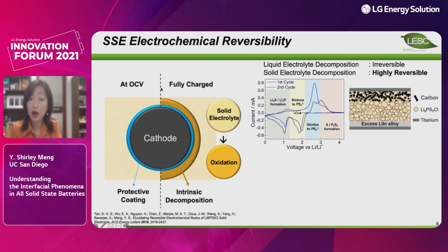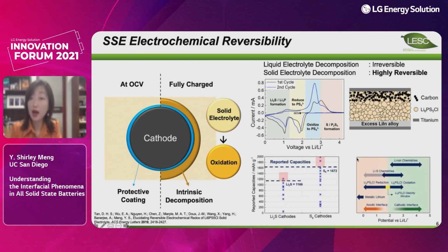So before we do any optimization of the cathode materials, when we charge the NMC to higher voltage, we run into the trouble of oxidizing the solid electrolyte. On NMC-based cathode materials, carbon additives are typically needed to enable cathode materials utilization. So we can't put a lot of carbon onto the solid cathode electrodes, because that will induce a lot of side reactions. So these stability issues with the solid electrolyte against the NMC cathode have been a big challenge.